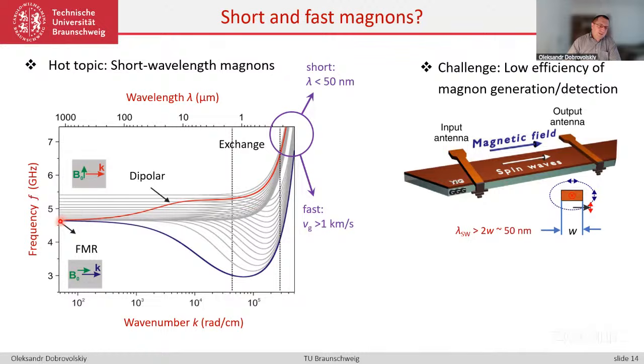And the dispersion doesn't start from zero. It starts from a particular frequency point. The physical meaning is a ferromagnetic resonance. So you have a well-defined frequency which corresponds to uniform precession in the limit when k is equal to zero. In the opposite limiting case, you are going to reach the exchange regime, where spin waves will be characterized by parabolic dispersion. And this regime is interesting because spin waves are short.